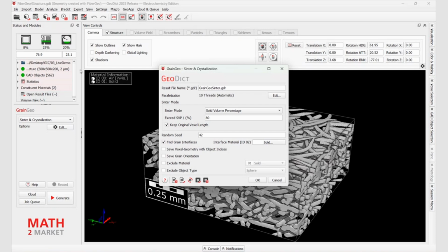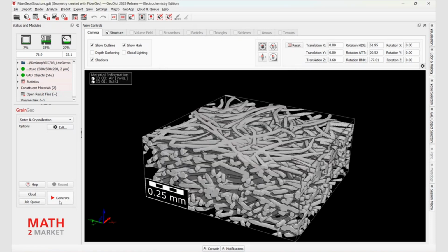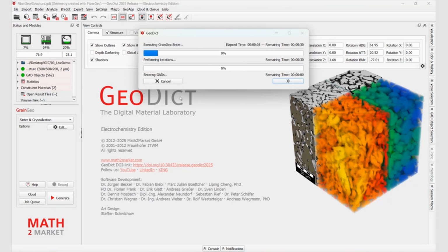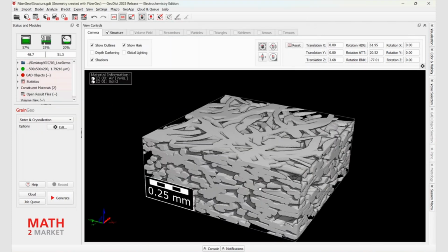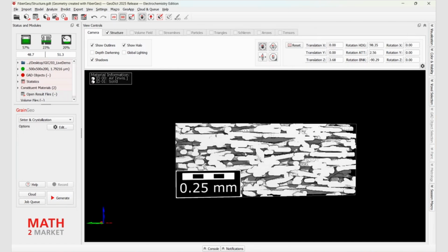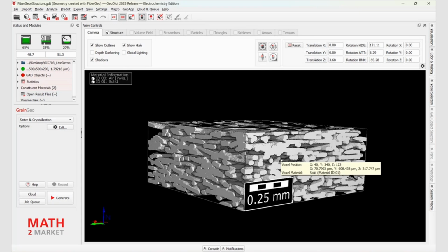So that's the effect, and I can set this to a shrinkage, and if I say it should shrink by 10%, it will compute for about 40 seconds, and as I said, it will keep the grammage but reduce the volume. It will keep the same voxel size and the same amount of voxels, but reduce the voxel length and make all the fibers a little bit thicker and glue together. Then it mimics the effect of a sintering process. You can check this out if it matches your models. So you see here, it looks a lot denser now if I do the sintering.